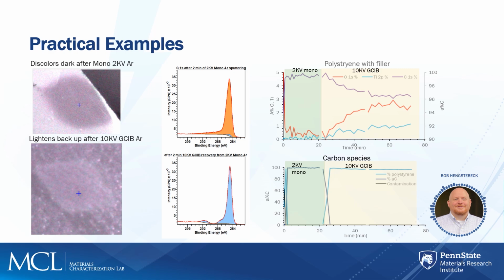And that orange you're looking at is a representation of what we see, and it also fits the chemistry of an amorphous carbon. If we then turn off that gun and turn on the GCIB source, we'll actually see the material recover. And it'll go back to being this white color that we would expect to see if we're profiling the material. We completely removed all of that dark coloring we were seeing.